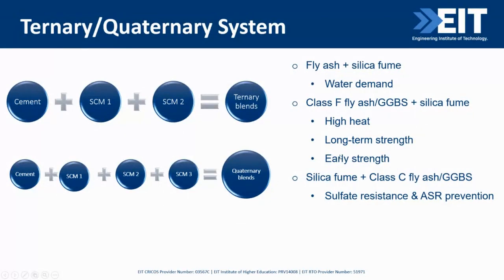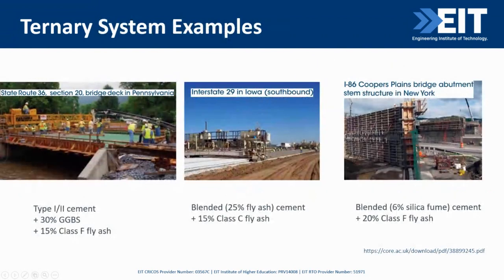Or the other way around, silica fume can compensate for low early strength of concrete using fly ash or GGBS. Silica fume also can reduce the normally high level of Class C fly ash or GGBS required for sulfate resistance and alkali silica reaction prevention. So here are a couple of examples of projects using ternary mixtures. In the first project, for a bridge deck, about 30% of GGBS and 15% of Class F fly ash were used in addition to the ordinary Portland cement.